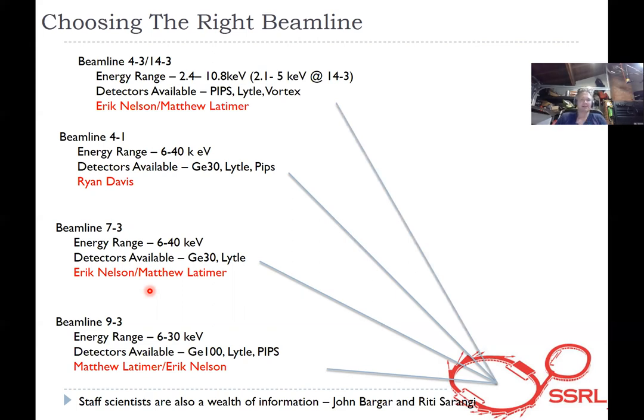And then we have our tender X-ray lines, 14.3 and 4.3. They go to low tender X-rays, so you can do chlorine and sulfur work. They do a lot of sulfur work at these beamlines. They have a PIPS, a Lytle detector, and a vortex detector. At 4.3, we now have a 7-element vortex with quantum electronics, meaning we can run these things pretty hot and still stay out of a dead time regime, which, if that doesn't mean anything to you, it will eventually. Meaning we can get better data quality faster is the take home.